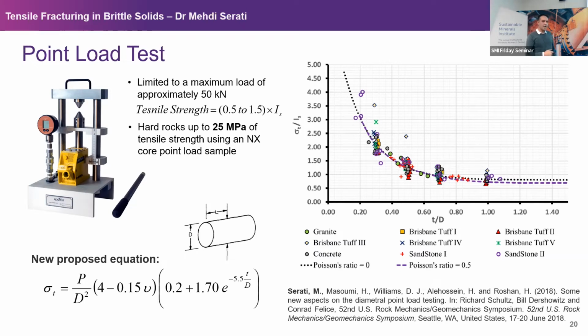By the way, you know that the ISRM standard suggests that if you are doing a point load test this way in a diametrical loading condition, the length of the sample needs to be always larger than the diameter. And it was always a question. Of course, we can test, you can try and see what happens. And if you do it experimentally, you see that the results become independent of the sample aspect ratio if that standard requirement is met. You can try it experimentally.